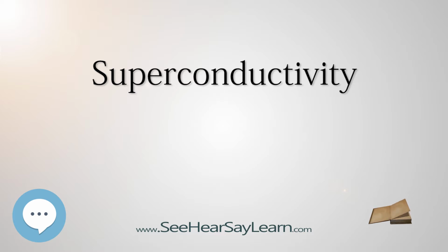Further history. The first practical application of superconductivity was developed in 1954 with Dudley Allen Buck's invention of the cryotron. Two superconductors with greatly different values of critical magnetic field are combined to produce a fast, simple switch for computer elements. Soon after discovering superconductivity in 1911, Kamerlingh-Onnes attempted to make an electromagnet with superconducting windings but found that relatively low magnetic fields destroyed superconductivity in the materials he investigated. Much later, in 1955, G. B. Yntema succeeded in constructing a small 0.7 Tesla iron core electromagnet with superconducting niobium wire windings.